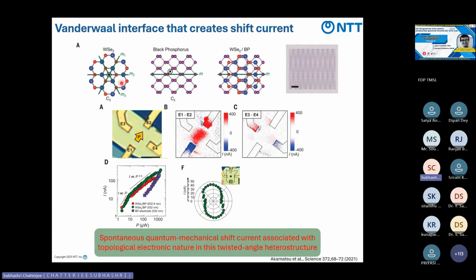In one report recently published in Science, they showed that if we use WSe2 and black phosphorus, and align them, stack them along the polar direction, we can break the symmetry. Due to that, we can achieve a Moire pattern which, unlike the graphene one, is not honeycomb or hexagonal style, but a different structure.